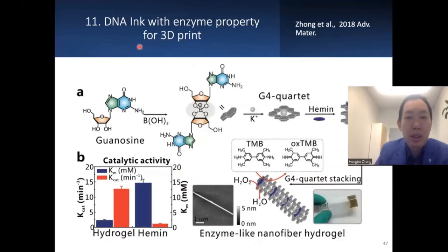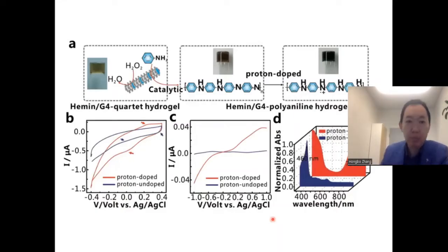And also we can use DNA ink to produce different kinds of wearable devices. So in this case, using DNA chemistry, we can build up a spatial structure. For example, as you can see from here, we can make such a structure, and then we can insert some enzyme like hemin into this structure, and they will grow in this way. So as you can see, this is the fiber-like structure we produced using this DNA chemistry. And they have a polymeric property. So if you put them in water, they will become hydrogel.